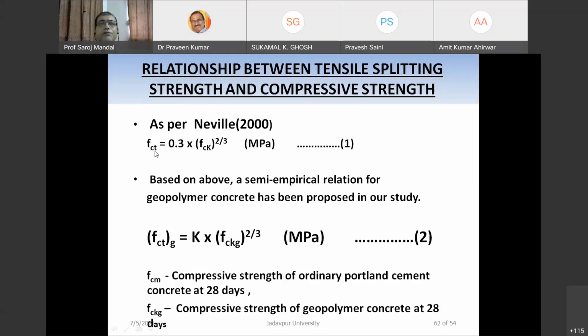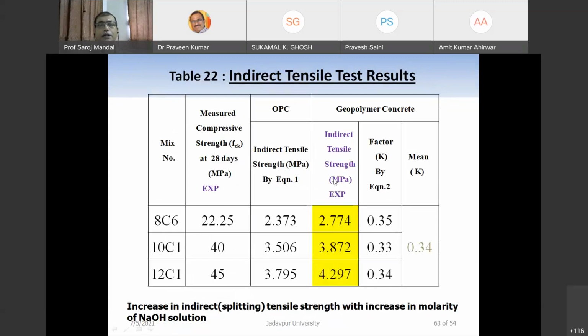This is as per Neville. We have used FCT, that is the tensile strength, is 0.3 times FCK. At the same time we try to calculate the K in terms of geopolymer. So for geopolymer compressive strength, what will be the geopolymer tensile strength and what will be the value of K? K for normal concrete is 0.3. Now we have tried with all 3 different molar solutions, that is, 3 different strength grades. This is basically the FCK strength of geopolymer concrete: 22.25, 40 and 45.